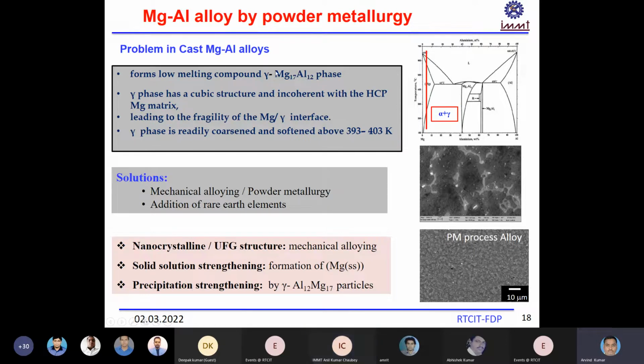But anyhow, you are getting this phase. So we have to avoid this phase and minimize it. Otherwise, our material will become completely brittle, and the interface between the magnesium and the gamma phase is also very fragile. That's why, when it is used in real conditions, many cracks are formed when there is much more gamma phase in this alloy. So our aim is to reduce the gamma phase in magnesium aluminum.